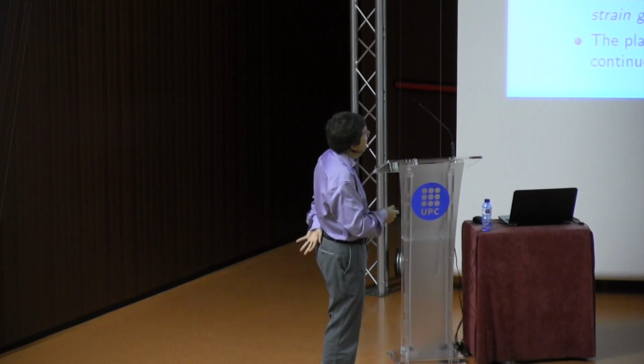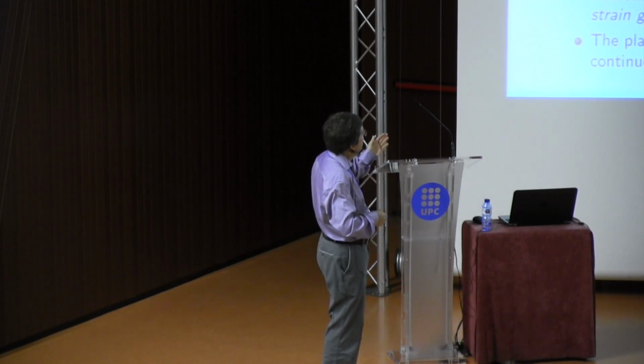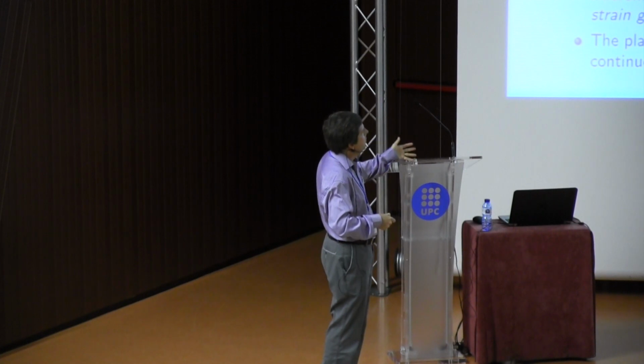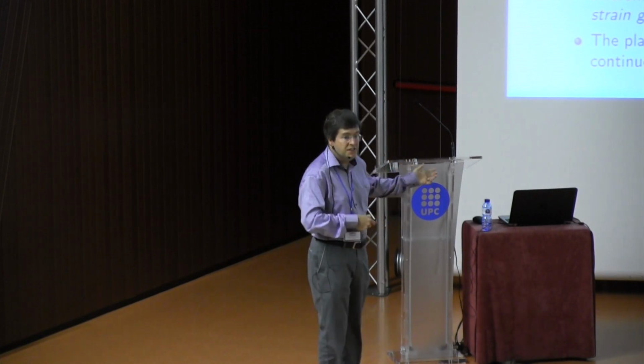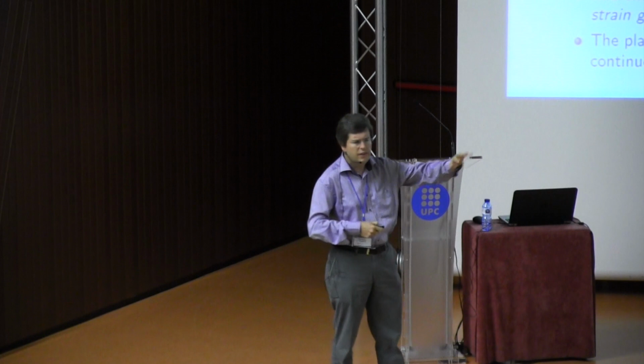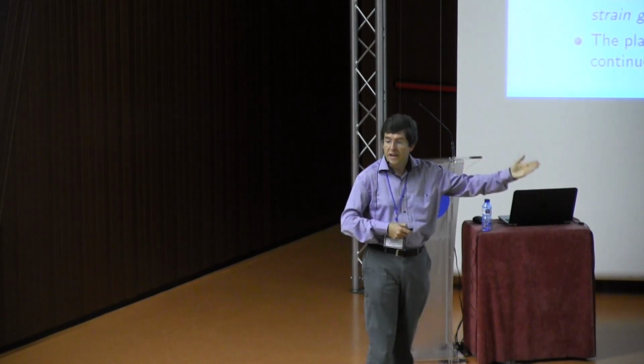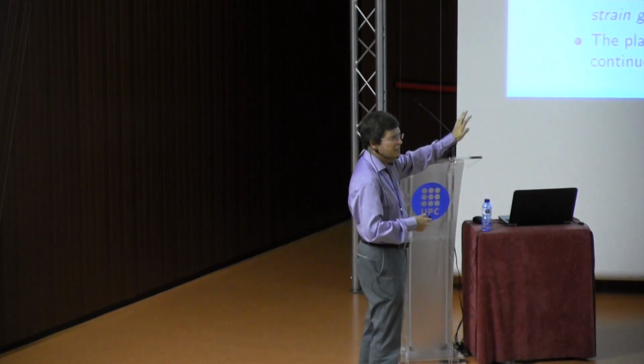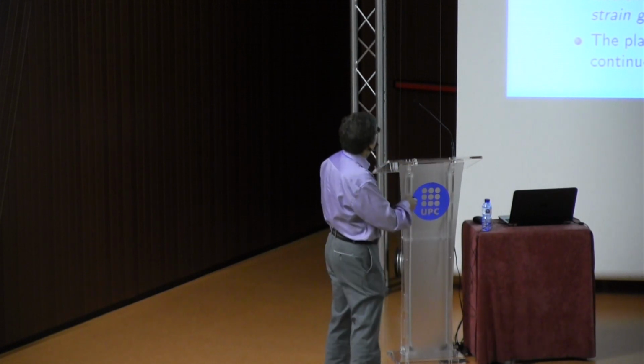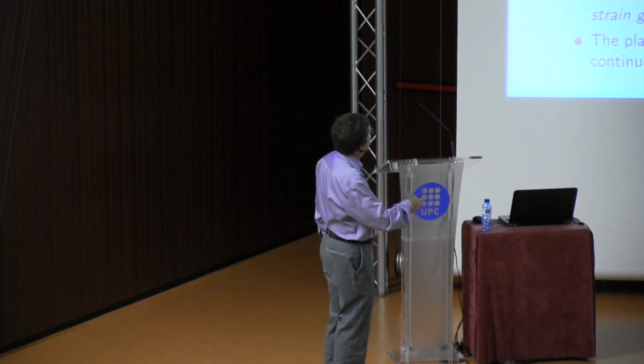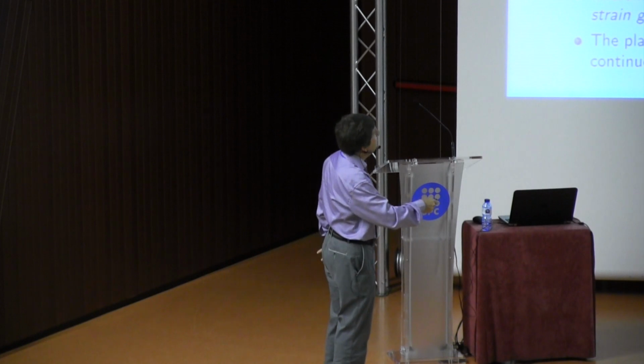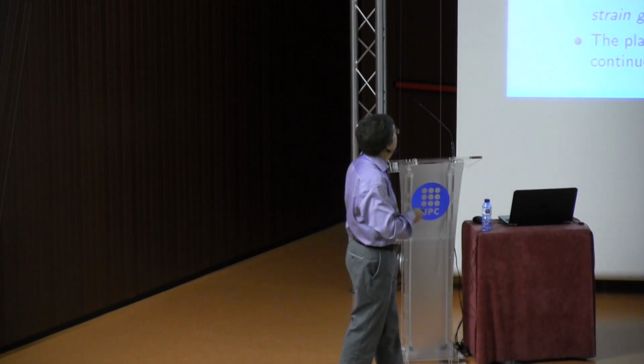The consistency condition is very easy in that case. So micromorphic plasticity is much simpler than strain gradient plasticity. There is no need for a front tracking of the plastic domain, for instance. The variable is defined everywhere, and you see that the plastic multiplier can be computed from the strain rate and the microplastic rate also.